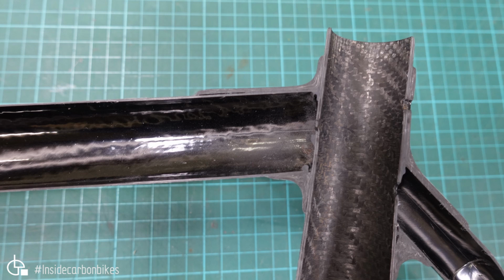Off to the lug where the seat tube and the top tube meet, and you can see a void through here, a little bit through here, but the one up at the top tube there, that's quite a large void. And it's right close to the edge, so that's less than ideal. The rest of it looks okay. There's been plenty of adhesive further through, a nice fillet through there, a little bit of voids through there, but that's insignificant really. And you can see where the seat tube has been ground or reamed to a nice fit to fit the seat post. But yeah, that void, that's less than ideal.